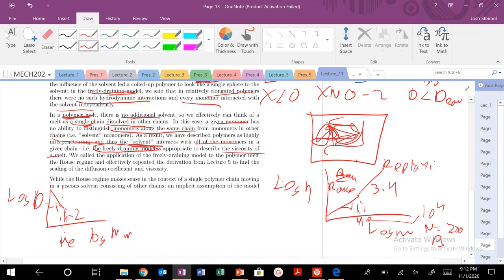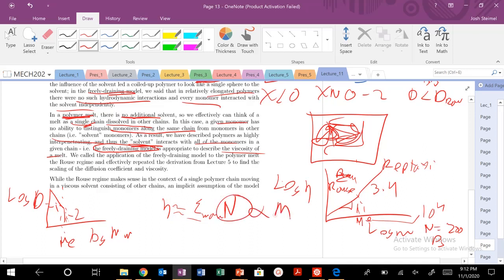So we are in the freely draining regime to describe viscosity in a melt. Looking back through lecture 5, we know that our viscosity is going to scale with our friction factor, which is the eta of the monomer. Since each monomer feels some friction from the fluid or solvent, and there are N monomers, your viscosity is going to scale with N. And N scales with molecular weight M — so that's how we get that first power-law scaling.